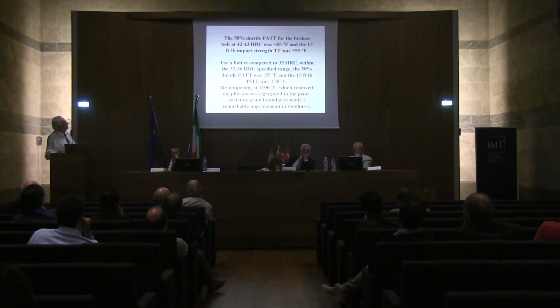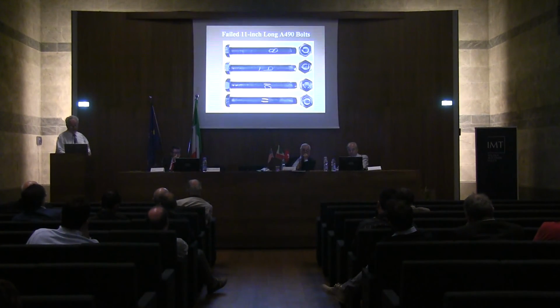The 50% ductile fracture appearance transition temperature was minus 55 instead of plus 85. That's a huge difference in the impact transition temperature. And the 15 foot-pound impact strength transition temperature was minus 140 instead of plus 55. So you can see a huge difference in toughness. Retempering at 1100 F, which removed the phosphorus segregation to the prior austenite grain boundaries, made a remarkable improvement in toughness.